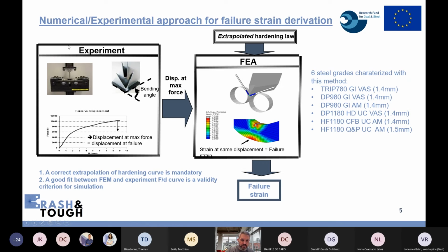So on the left side, first we perform the experimental test. We will measure the force versus the displacement, and we will take the displacement at failure, which is detected by the load drop. So here we take the value just before the load drop, the maximal force, and we will inject this displacement into a finite element simulation, which will take into account a fine plasticity description of the material, the correct setup, the correct thickness, the correct gap, and we will virtually measure the fracture strain on the sample, which is actually the strain reached when the displacement at failure is reached experimentally, and then we can have the fracture strain.